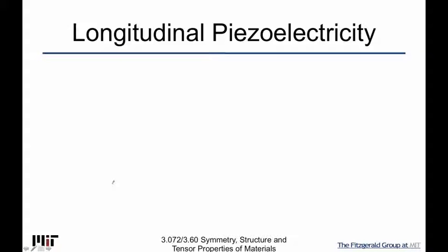So the longitudinal piezoelectric effect is how I would experimentally map this out. You probably have noticed that, in this part of Maxwell's equations I described, the charge on a surface and the charge through the volume are really not distinguished. Mathematically, they all come out in Maxwell's equations as if they're on the surface, whether I have little three-dimensional dipoles through the volume or whether they actually do have charge on the surface.